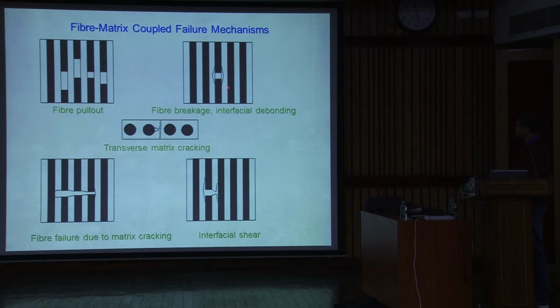Then this one can lead to interfacial debonding. The fiber has broken here. Now the stress distribution takes place and the bond between fiber and the matrix near this break becomes weak and there is an interfacial debonding. Sometimes because of this interfacial debonding, the crack will propagate inside and instead of going further, it may go in the thickness direction. So, this is called transverse matrix cracking.